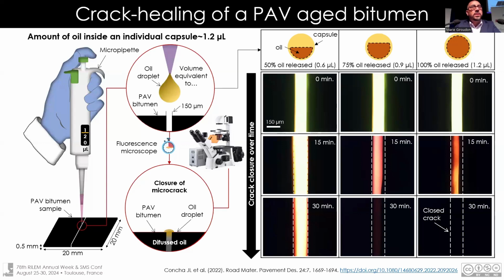There are different challenges in order to evaluate the self-healing properties in bituminous materials. In this slide, you can see a very beautiful and pretty easy test in order to evaluate crack healing over time, in this case using fluorescent microscopy. You can evaluate the closing of the crack over time, in 30 minutes, using different rejuvenators or a simulation of the deformation of the capsules in the materials.